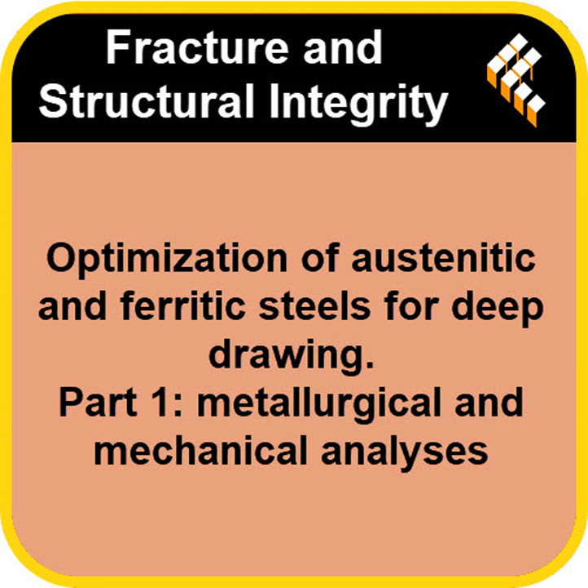Wow, double the impact. Yeah. So if you pay the premium for that highly formable austenitic steel, you have to nail the process, especially lubrication. Otherwise, you're essentially throwing away a huge chunk of the material's potential. So it really brings us back to that selection dilemma. When you're choosing a stainless steel for deep drawing, you're weighing things up. You've got the austenitic grade with its fantastic formability, its high work hardening, but it costs more and its price fluctuates. Versus the ferritic option, much cheaper, stable price, but less inherently formable.